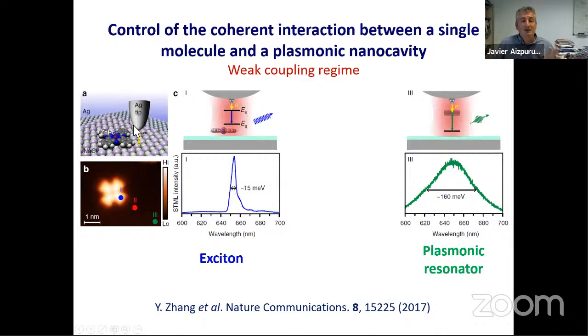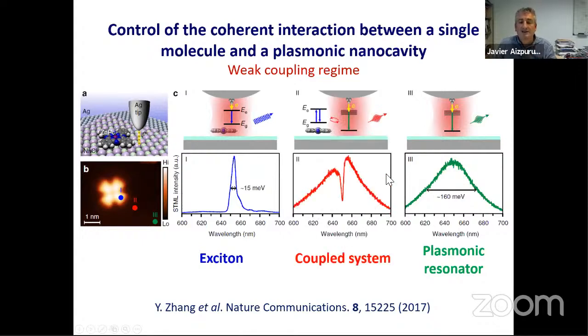But now, if you put the cavity in between, with the exciton of the molecule and the plasmon of the cavity interacting, look at the result. The result is amazing. It's a perfect interference between this plasmonic mode and this excitonic mode, with the emergence of a destructive interference, often called a Fano-like profile, a Fano interference, right? Of a continuum, a broad resonance, and a discrete state, a thinner resonance. And you can describe this even classically with two harmonic oscillators, a broadband harmonic oscillator and a thin harmonic oscillator, and they would provide exactly this type of spectroscopy, right? And this is an example of weak coupling.